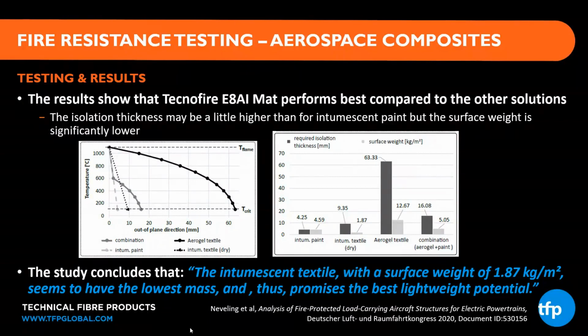Now, keep in mind, it's a fairly low density material, our dry intumescent textile. So even though it starts at 9.35 millimeters thick, that can compress quite readily. So very, very commonly through processing, Tecnofire will be reduced to 1/3 of its original thickness. But the key takeaway was the fact that the intumescent textile with a surface weight of 1.87 kilograms per square meter seems to have the lowest mass and thus promises the best lightweight potential. So Tecnofire, because of how light it was in the scenario, to protect to that critical temperature, it was the choice from this study.